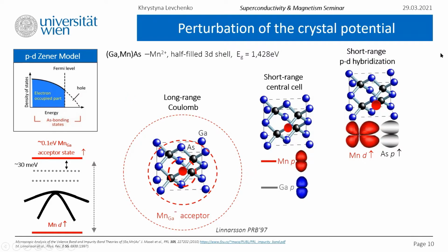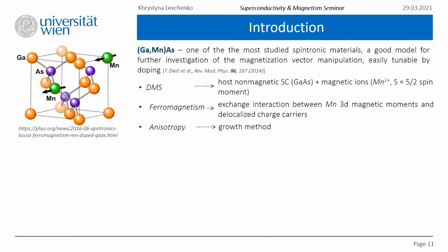With a concentration of manganese above 1%, we arrive at gallium manganese arsenide as we know it, one of the best studied semiconductor spintronics materials. Again, it is a DMS, dilute magnetic semiconductor, which consists of a non-magnetic base, well-known, well-established, and well-compatible with existing technology, doped with some transition metal ions, usually manganese, that has a spin moment of 5/2. It's a ferromagnet, where the magnetism is governed by the exchange interaction between manganese 3d moments and delocalized charge carriers. So it means that it's magnetic below some critical temperature, called the Curie temperature, and paramagnetic above it.